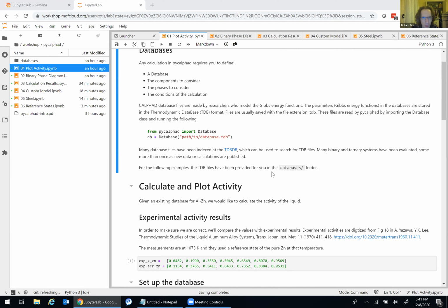For the spinodal, it's a little trickier. The way that you would need to do that is you would probably have to compute the stability function yourself. So you would probably take a random sample of the energy surface, and then you would have to compute the stability function and then look for sign changes. And then when you find a sign change, you would plot that on top of the phase diagram if you wanted to superimpose it on the phase diagram.